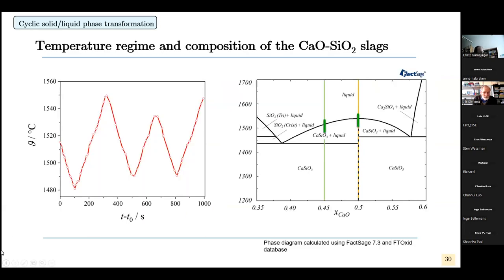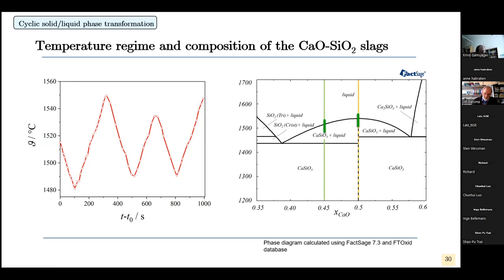Here is the temperature treatment we used. We look at two different compositions: one where diffusion is required during melting and solidification, and the other composition at the maximum in the phase diagram where no diffusion is required. We look at the differences between these two processes — this is incongruent melting and solidification versus congruent melting and solidification.